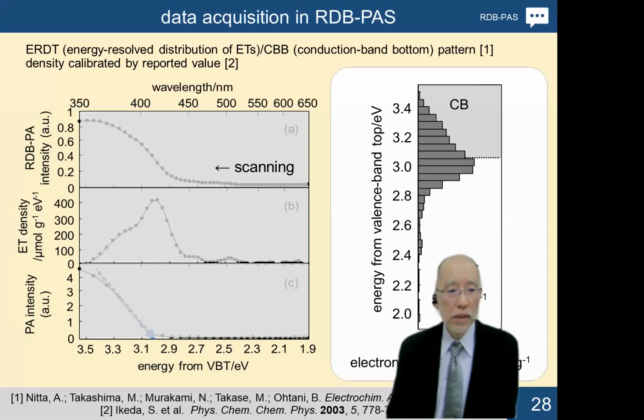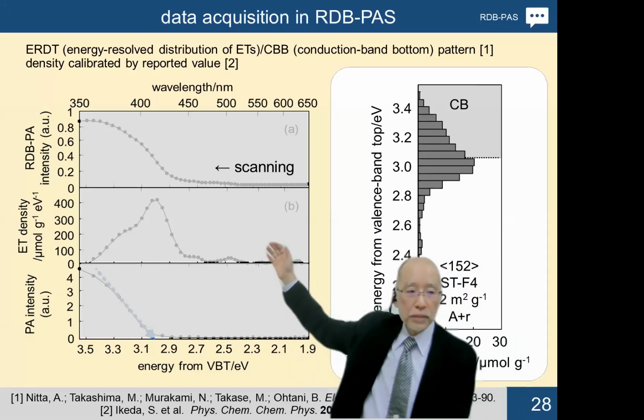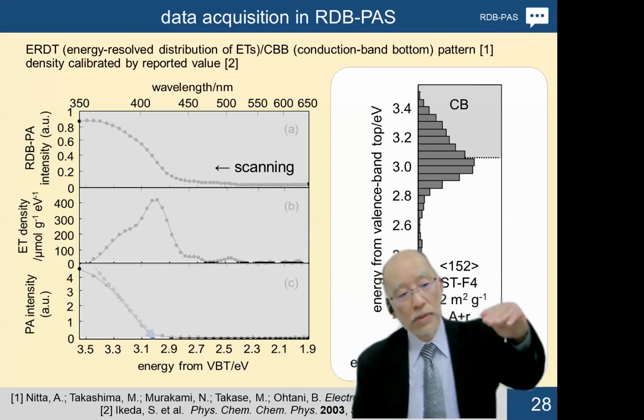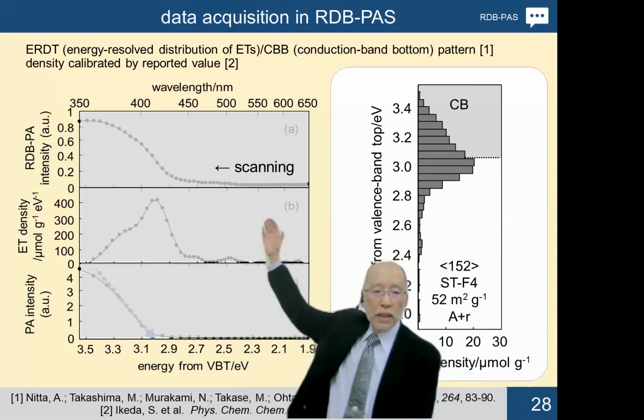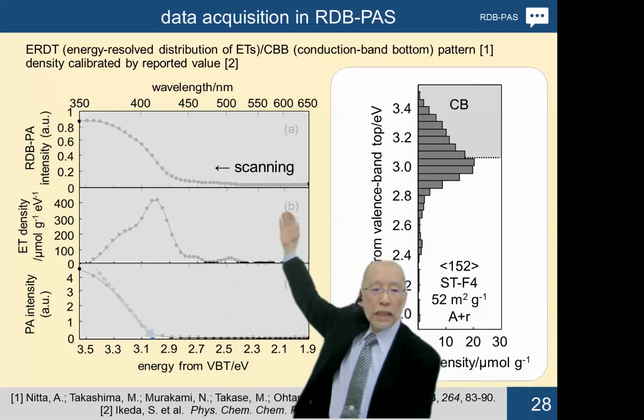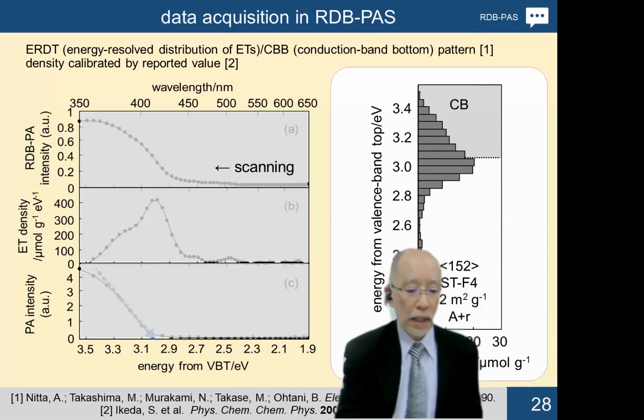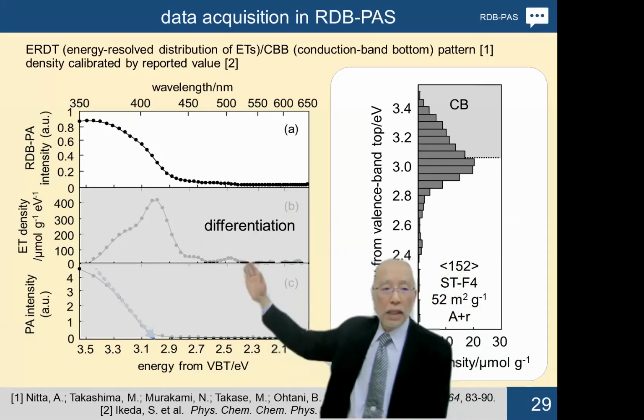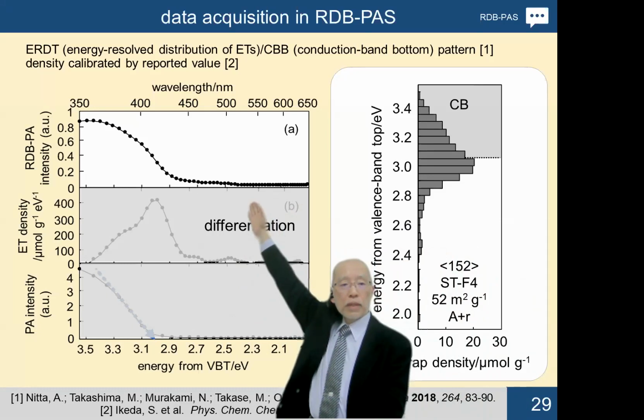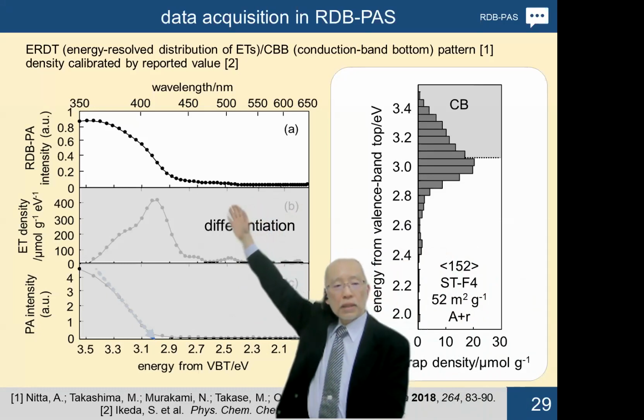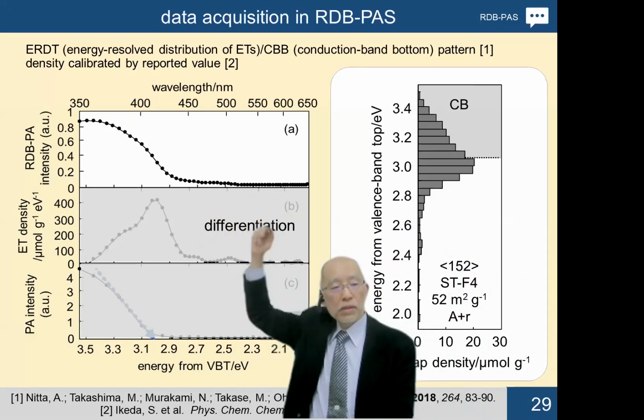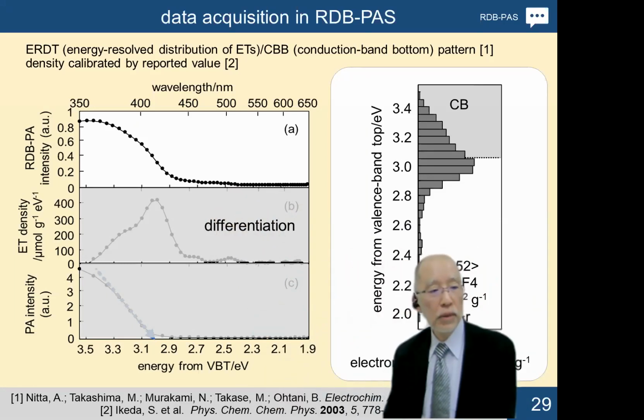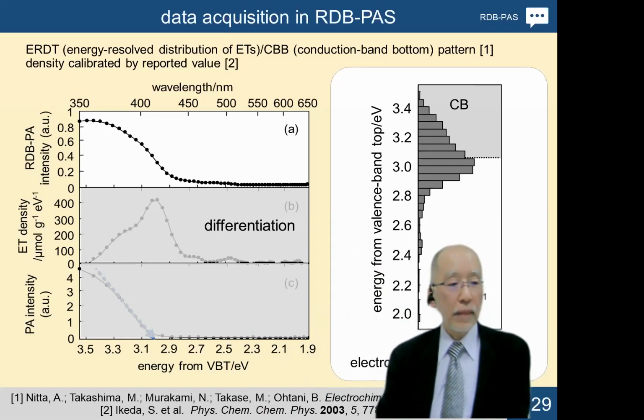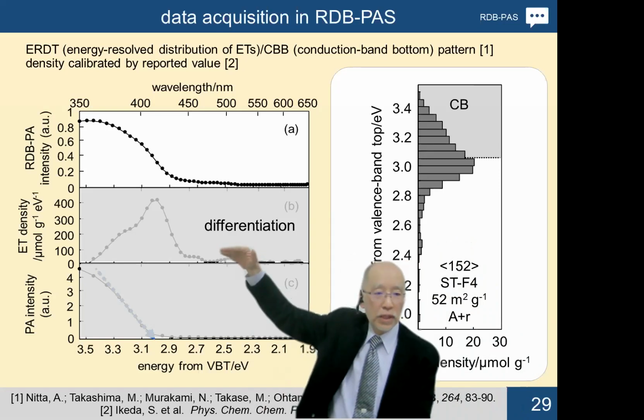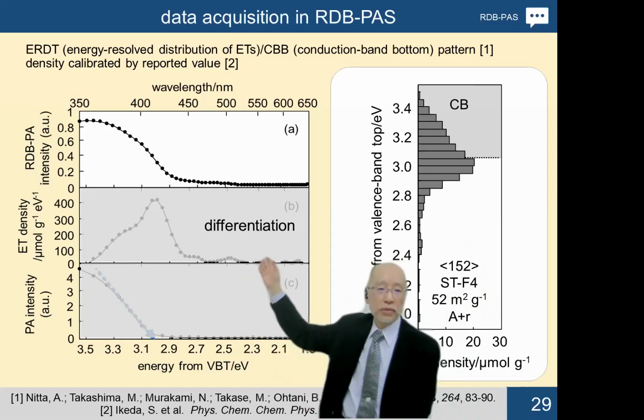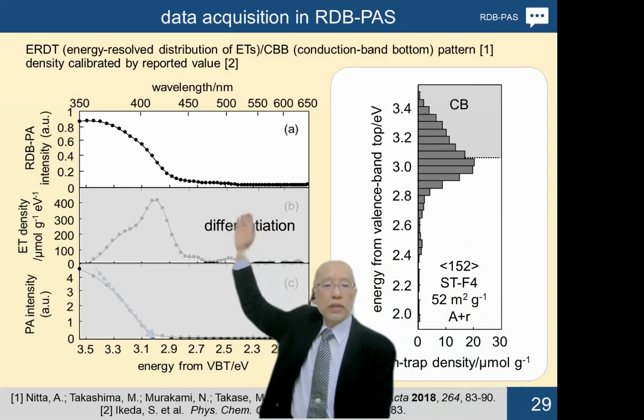And these are the actual results. The top panel is the result of photoacoustic signal change by scanning the excitation light from the longer wavelength side to the shorter wavelength side. The accumulation starts from this wavelength, about 550, and increases gradually, and suddenly steeply increases at about 430 nanometers. And then at 350 nanometers, that is almost saturated. So this is the total accumulation. In this lower energy region, the accumulation is not so much.